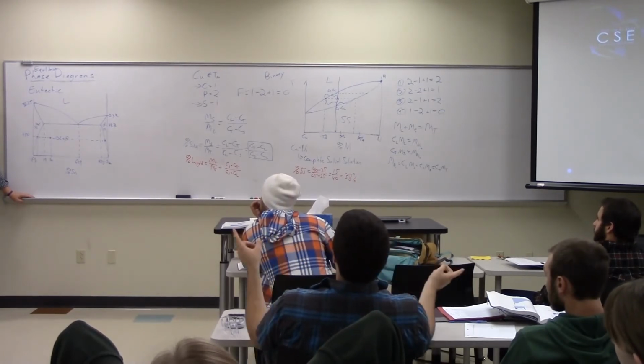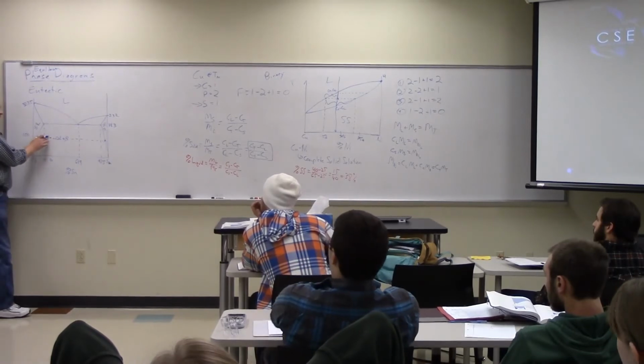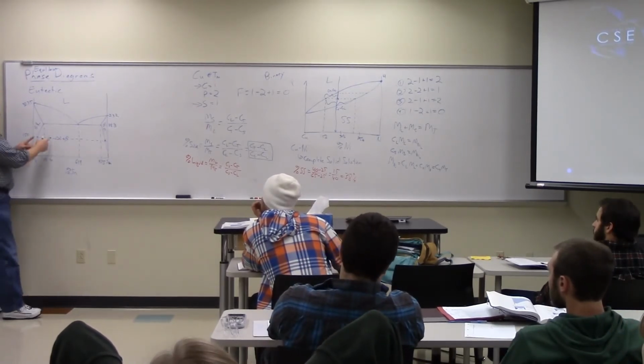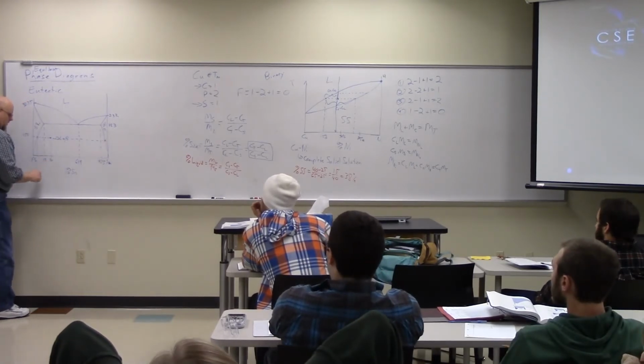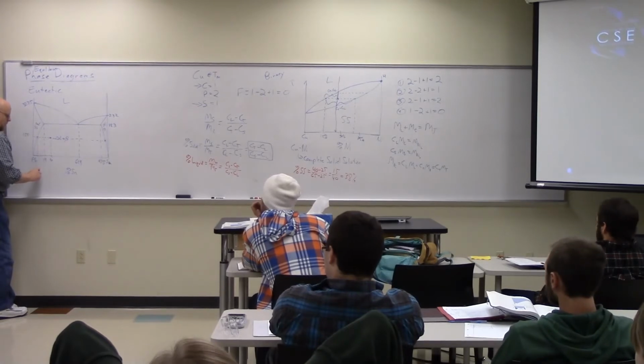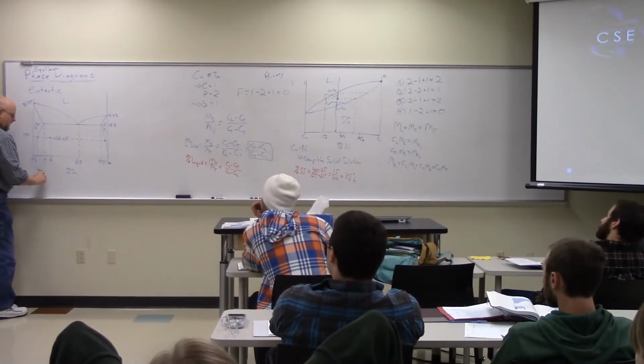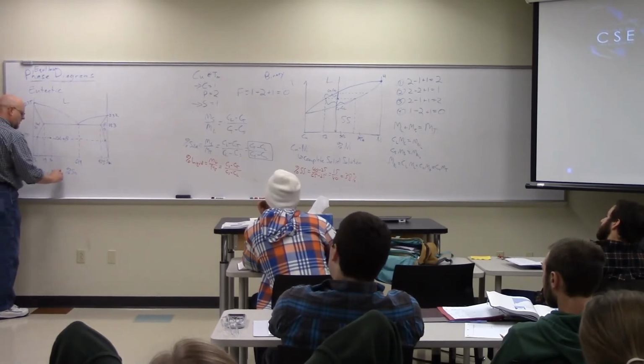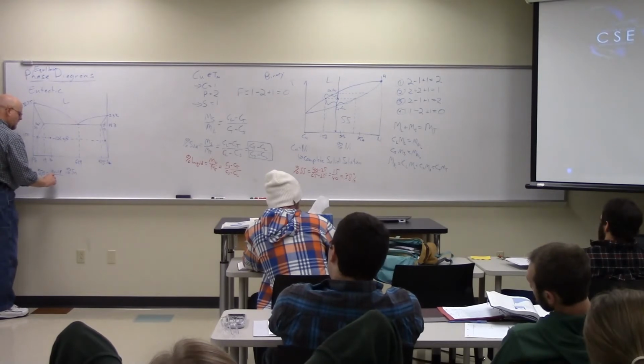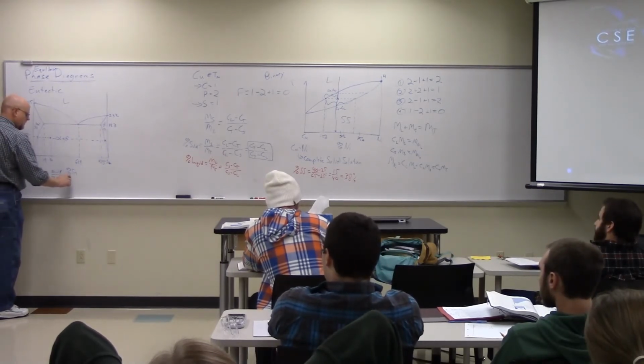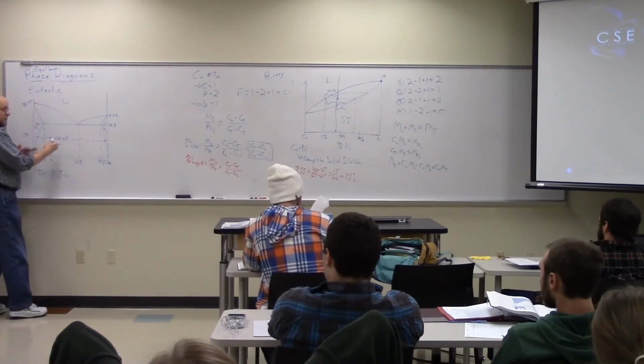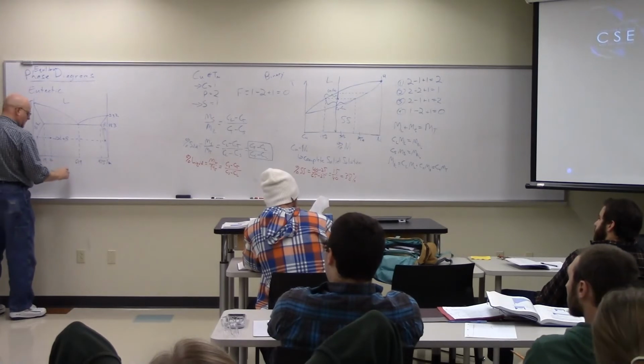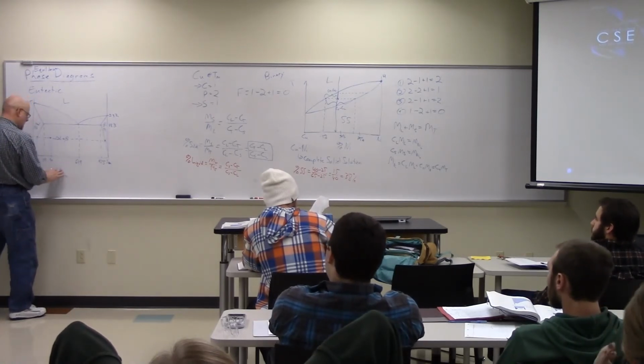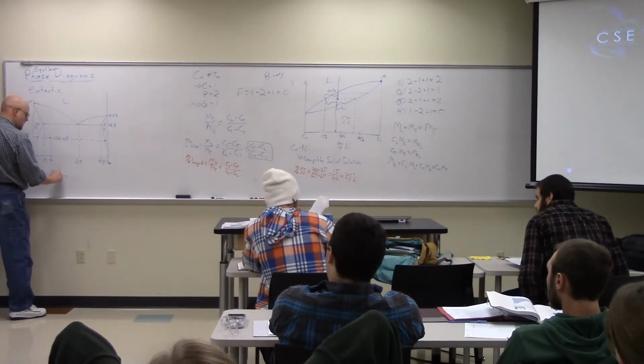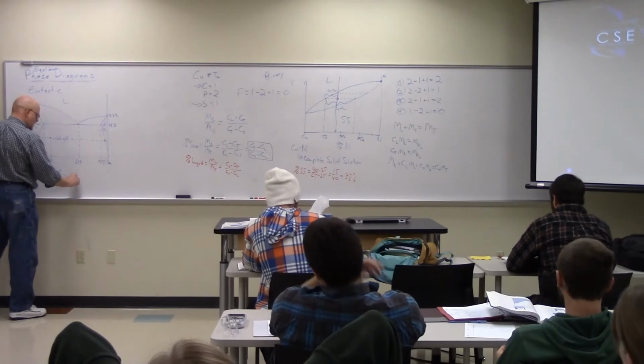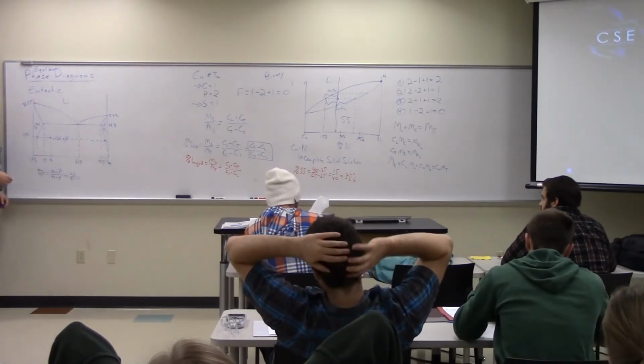We find those percentages by doing the inverse lever rule. The inverse lever rule tells me how much alpha I have and how much beta I have. So I have this divided by this. The percent beta is going to equal 30 minus 19 divided by 99 minus 19. So whatever that would be. Again, these numbers are made up, because you have to pull them off of a real diagram. It's not 19, I'm sorry, it's 8. So that becomes 22 divided by 91, whatever percent that is, that's the percent beta.